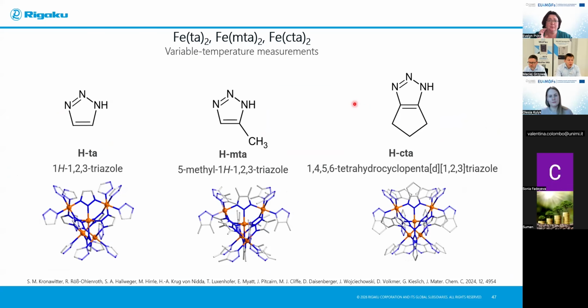So here's an example of follow-up on that research. You find the reference on the bottom. The authors, the chemists, want to prove that they can lock the framework against changing phase transition. So let's say they want to control the phase transition, so they change the design of the material. To do this, they came up with the clever idea to change the linker to being more stiff, to provide more stiffness to the framework itself. So they grow the linker and provide the materials, and indeed they lock in the transition.